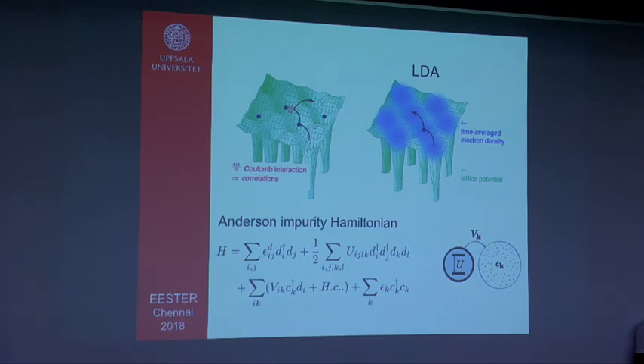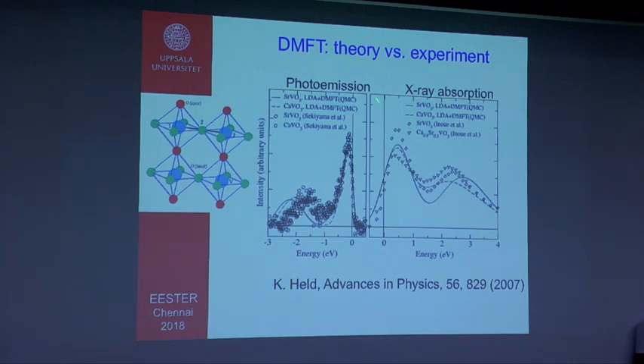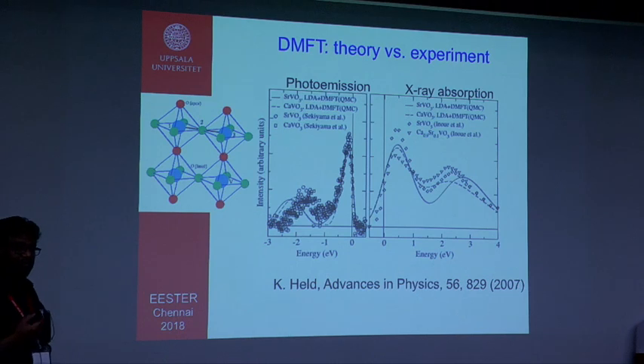So if you follow these procedures, then you can generate some very nice results. You have some data of photoemission and X-ray absorption. Photoemission means you are probing the occupied part, and X-ray absorption means you are probing the unoccupied part. For different oxide systems, strontium vanadate, calcium vanadate, with LDA plus DMFT and with some experiments, the continuous curves are the theory results, and these are the experimental results. You see these lower Hubbard band and upper Hubbard band coming in very nicely, and you have the quasi-particle peak at the Fermi level. All these fantastic features come out if you do dynamical mean field theory.